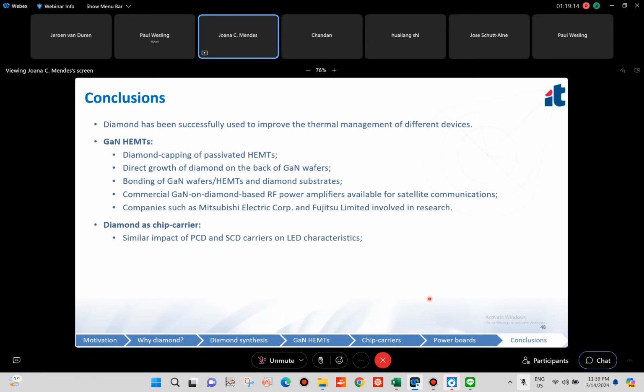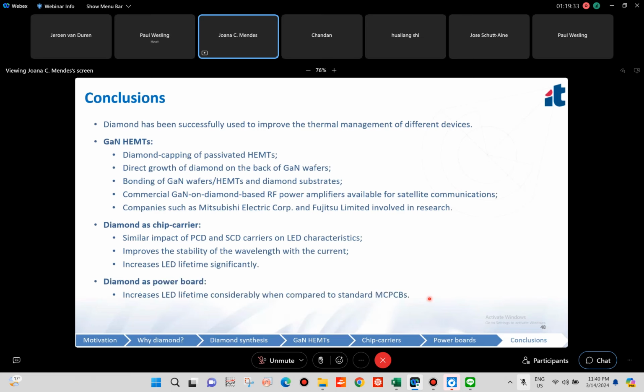We can also use diamond as a chip carrier, and we estimated that we would have a similar impact of polycrystalline diamond and single crystalline diamond carriers on the LED characteristics. We observed that these diamond carriers will improve the stability of the wavelength, and they will increase the LED lifetime significantly. And finally, if we use diamond as a power board, we increase the lifetime of the LED considerably when compared to standard metal core printed circuit boards.